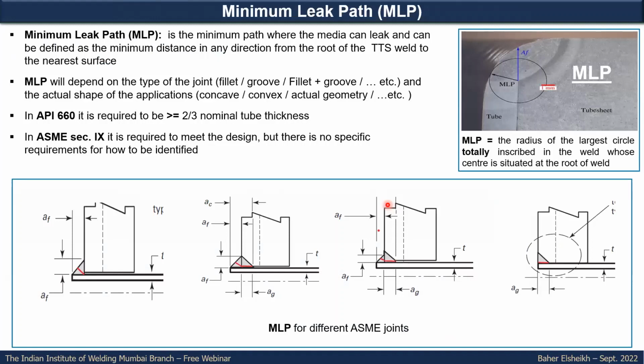Minimum leak path is the minimum path where the media can leak, and it can be defined as the minimum distance in any direction from the root of the tube-to-tubesheet weld to the nearest surface. As you can see here in this photo, it is the radius of the largest circle which can be totally inscribed inside the weld, and whose center is the weld root. So you might in the drawing have some circles, but it should be the greatest one, which is fully enclosed. So the radius of this one will be the minimum leak path.